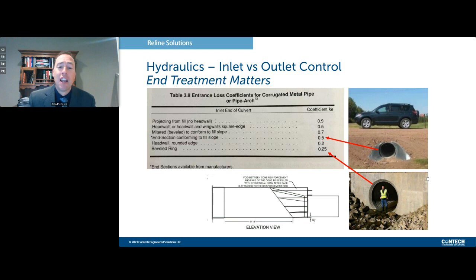That's one of the best. In some cases, we've been able to actually use an increaser at the inlet end. So even though our liner pipe would say be 30 inches in diameter, the inlet itself would be 48 inches. And there, because we're only concerned about the inlet, we're able to increase the diameter of that inlet and potentially increase your hydraulics. Now, the one drawback with that is you do have to have a little more right of way and be able to use this structure, because you've got to extend that out further in order to get to the larger diameter.